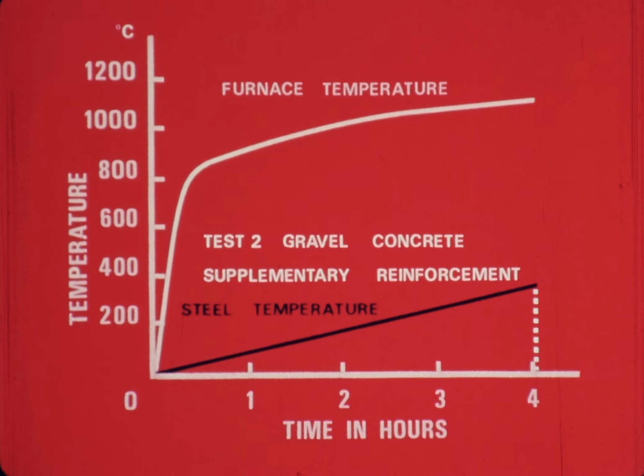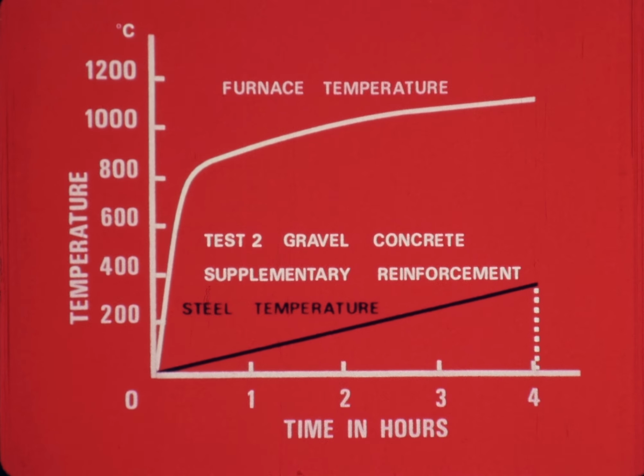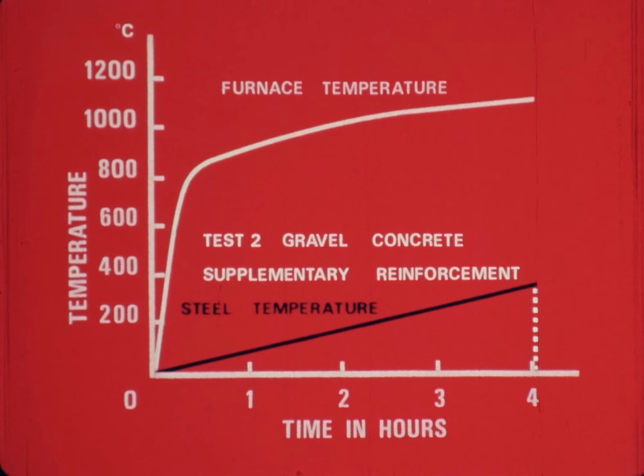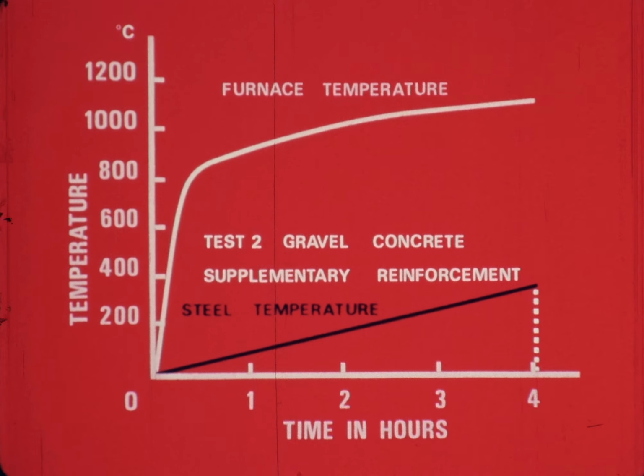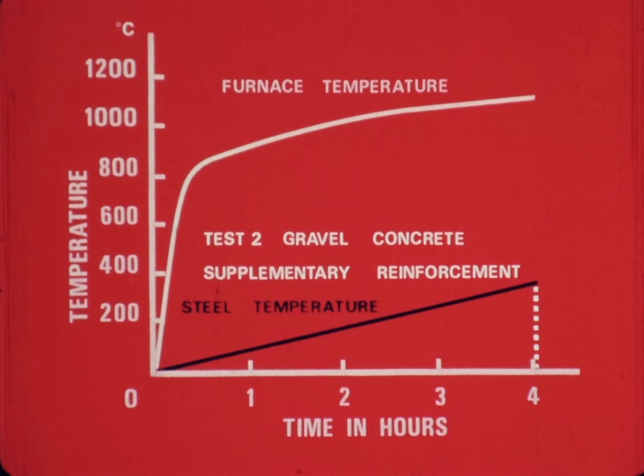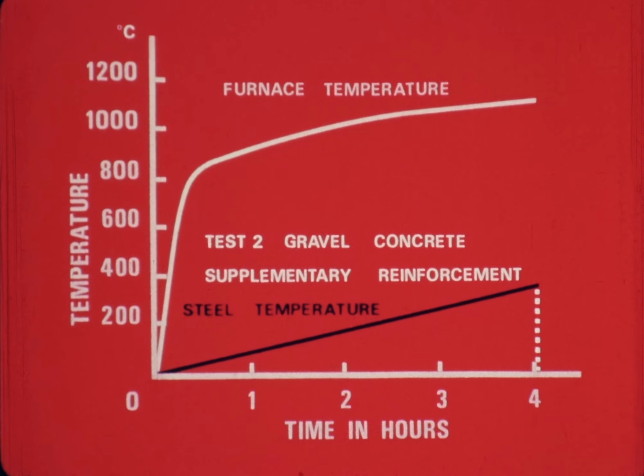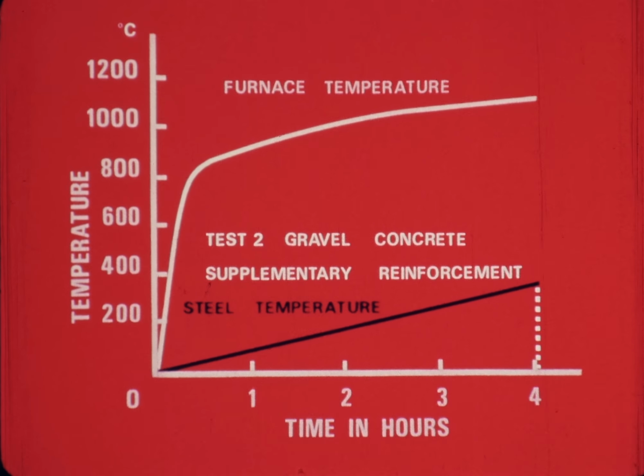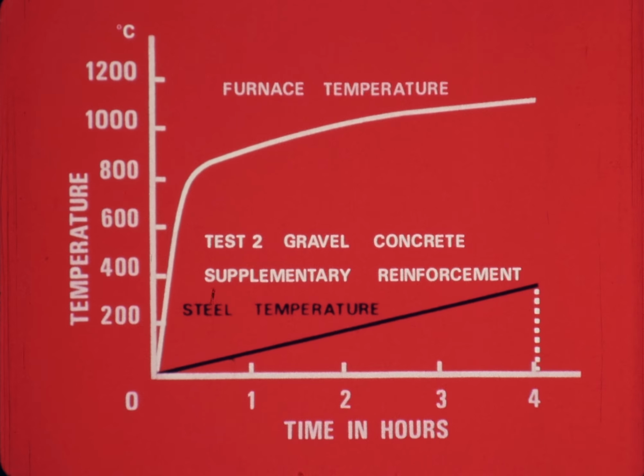In the second test, supplementary reinforcement was provided. This held the concrete in place and protected the main reinforcing steel, so that its temperature rose more slowly. After 2 hours, it reached only 200, and after 4 hours, only 340 degrees. This beam did not fail.